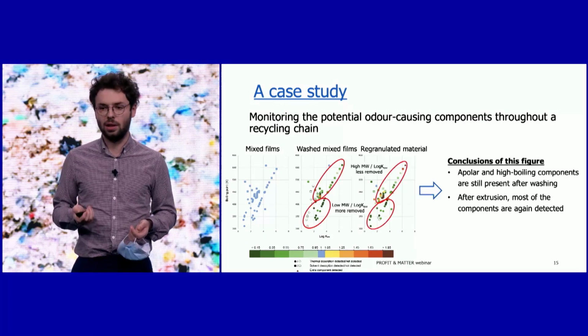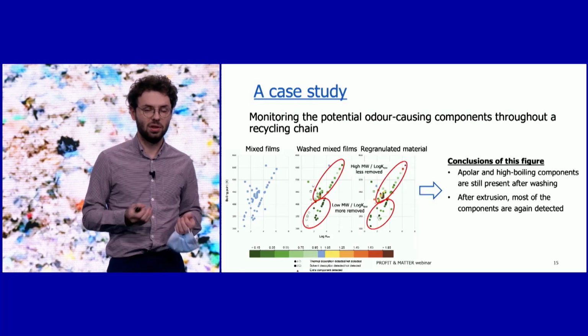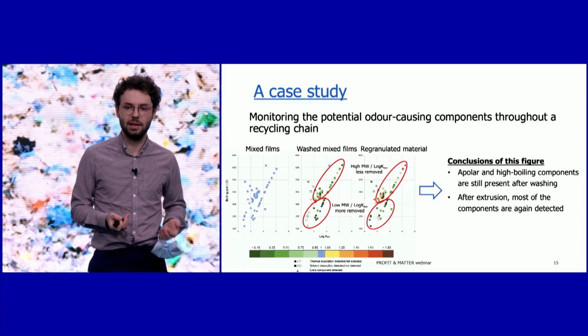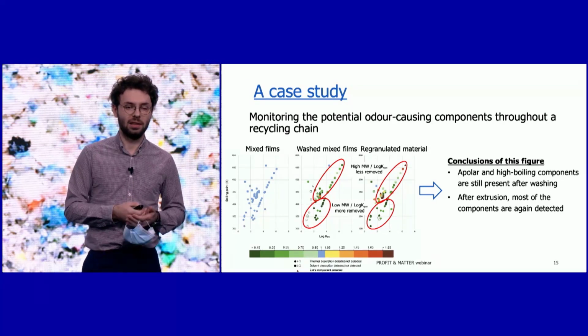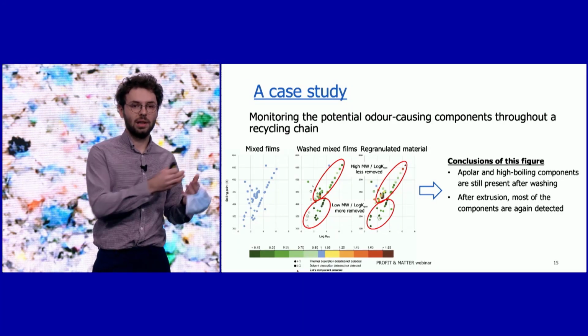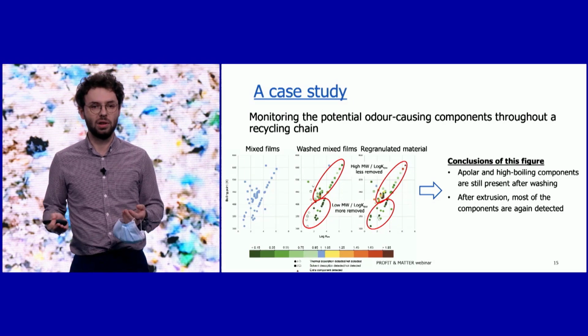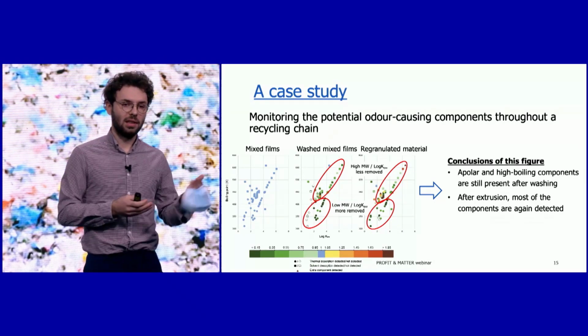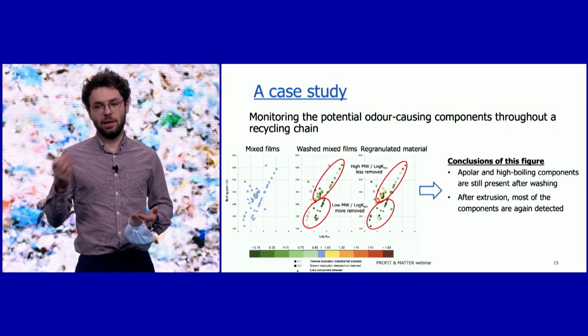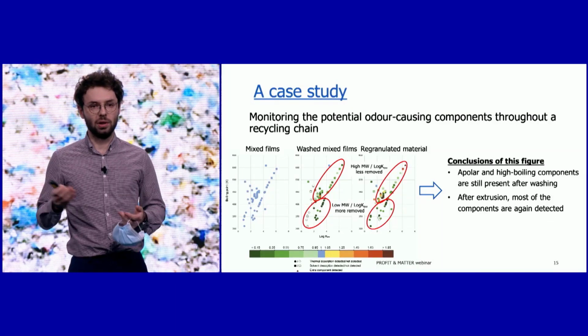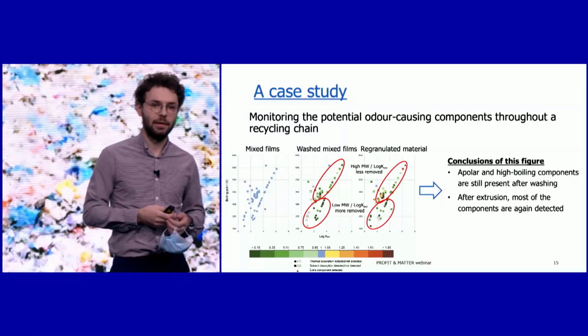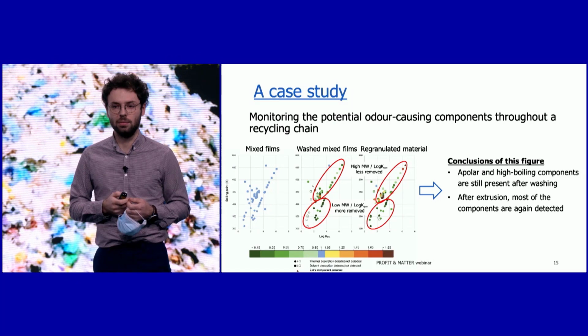After washing, we saw that most of the odor components were reduced in intensity, which is, of course, because they were washed. But also what we saw is that the more polar components were more removed, since their color is more dark, than the more apolar components. This can be explained by the fact that we used water as a washing medium.